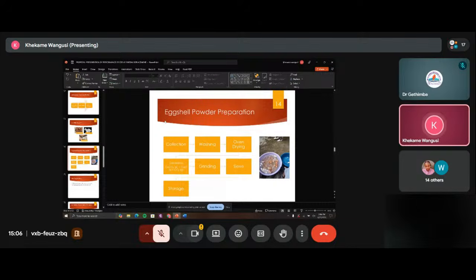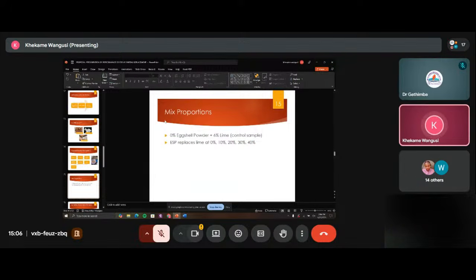Eggshells are collected, washed, oven dried, heated to convert calcium carbonate to calcium oxide, and ground into fine powder. The powder is then sieved to obtain a uniform particle size suitable for laboratory testing. A control sample containing 0% eggshell powder and 6% lime is prepared. Lime is then partially replaced with eggshell powder at 10%, 20%, 30%, and 40% to assess the performance at different replacement levels.